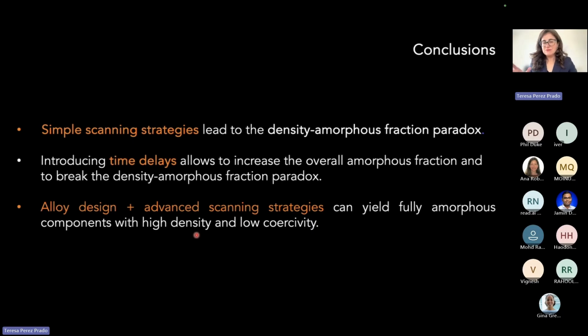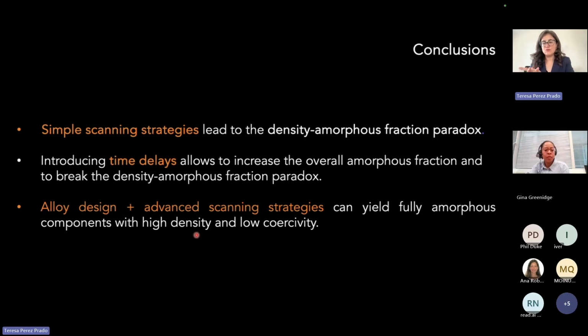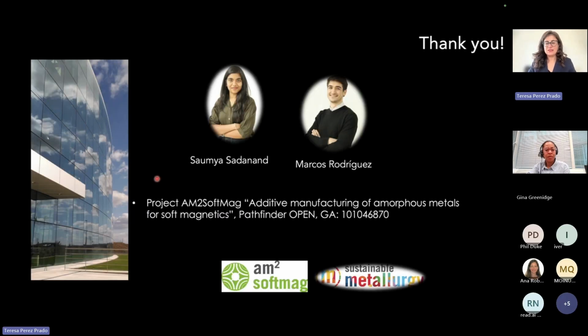So, just 3 conclusions. When we use simple scanning strategies, we always face this density-amorphous fraction paradox, especially with the commercial alloys. If we introduce time delays, this helps to really reverse this paradox. And then we need a combination of alloy design and these advanced scanning strategies. With that, we can really make complex shape components with fully amorphous phases and relatively high density, which is what we want. Of course, there is a lot of work still to be done, but I think there was major progress within this project.